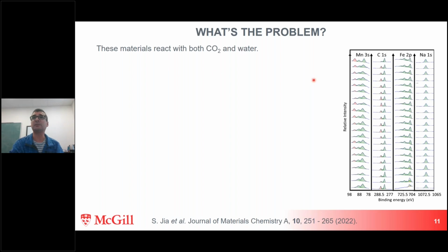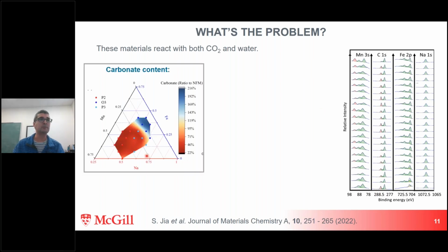So we did XPS. And in pink, you can see this carbonate peak changes really dramatically with composition. And in fact, if we do a map, we can see that with iron, you get more and more carbonate. So being down here means that you're reacting less with carbon dioxide. So that's really encouraging. That's great.